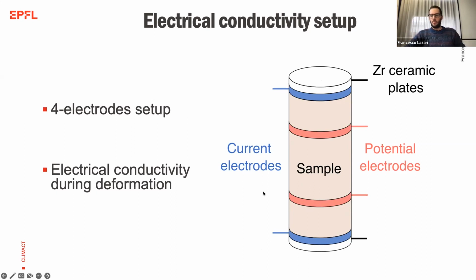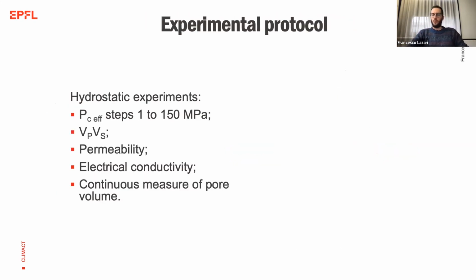It's a really simple setup, but it took a long while to calibrate and get it to work, because this thing has to resist pressures up to 2000 atmospheres, so it needs to be really solid. Since it's a new method, we had to benchmark and calibrate it. To do so, we did some hydrostatic experiments, which are experiments in which we put a rock in the machine and we increase the pressure around the rock isotropically. So we don't deform the rock with the 2 pistons, but we just load it with the oil.